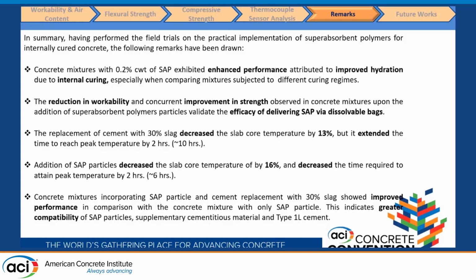We also found that there's a reduction in the core temperature of the slabs by the replacement of 30% of cement using slag. And we also found that incorporating SAP in mixtures with cement replacement by slag improved the performance when compared with SAP alone. So it shows the compatibility of SAP particles with supplementary cementitious materials as well as Type 1L cement.